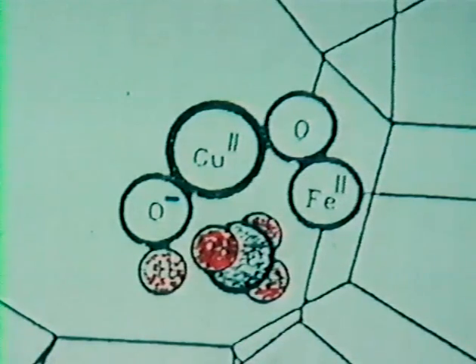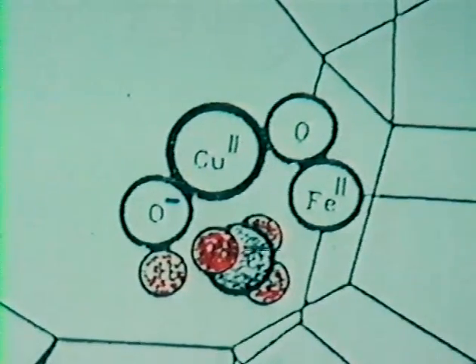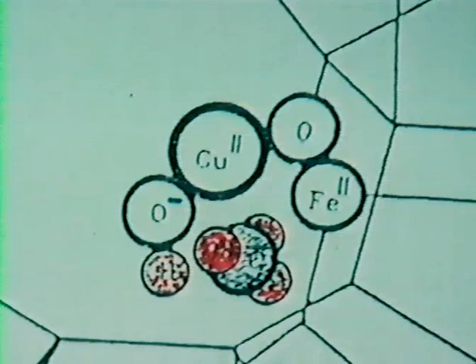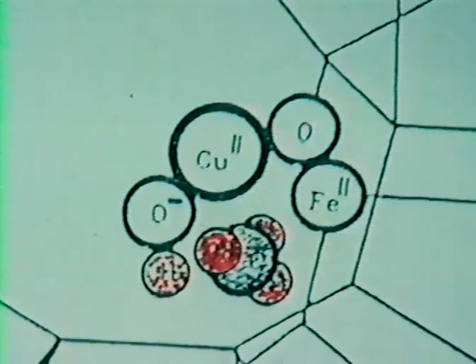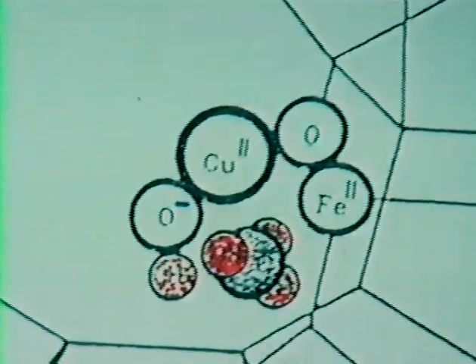Now the problem with the ZSM5 is there are pores in it, and you make methoxide, and you make formaldehyde, and you make methanol at high pressures. But as it proceeds through the pores, it gets oxidized further to higher oxidation products. Zeolites have, as we know, very high internal surface areas. We also know that in oxidative coupling, the requirement is that the surface areas ought to be very low.